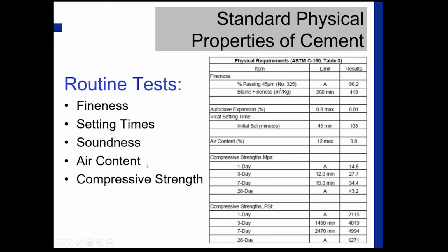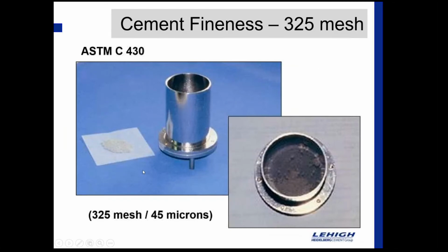Okay, so let's move into some of the physical properties of cement. And here we're going to look at things like fineness, setting time, soundness, air content, and compressive strength. The first up is the measure of fineness. One way that's measured is the 325 mesh sieve or the 45 micron sieve. Here, again, we're just putting a 1 gram sample into that sieve. And you have to understand, when we talk about 325 mesh, it's not 325 mesh per square inch, it's 325 meshes per linear inch.